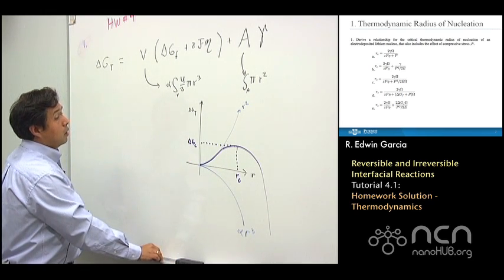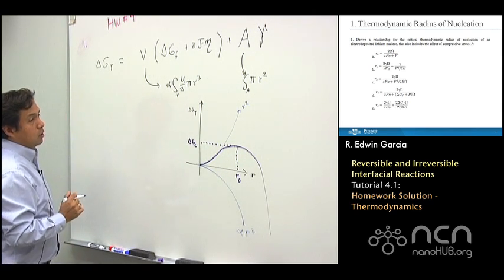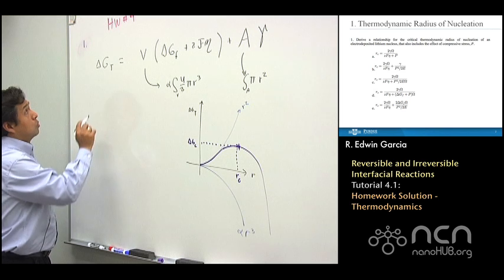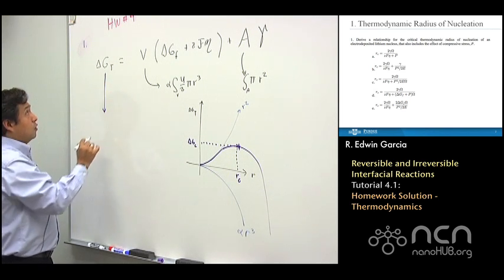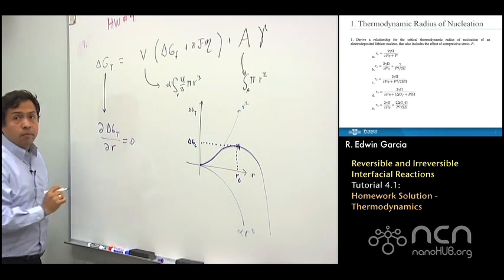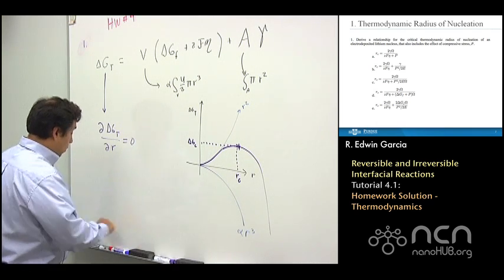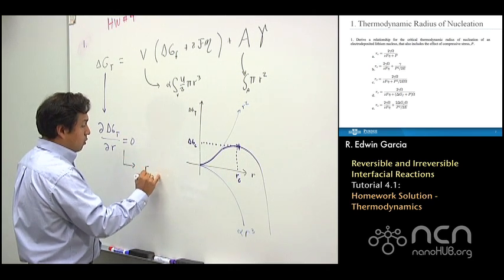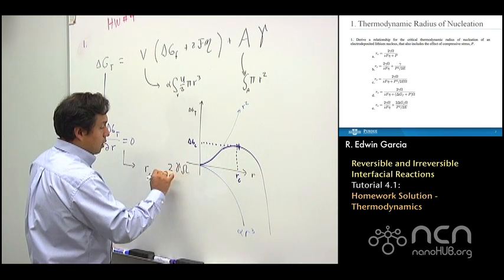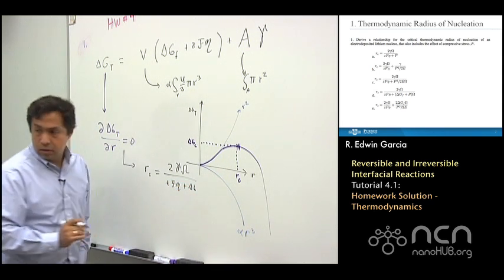If you go over the steps in the absence of mechanical stress, that value corresponds to maximizing that function, where you basically calculate the extremum. If you do that, you will find that the critical radius goes as 2 gamma omega over ZF eta plus delta G. Oh, there's an omega missing here.